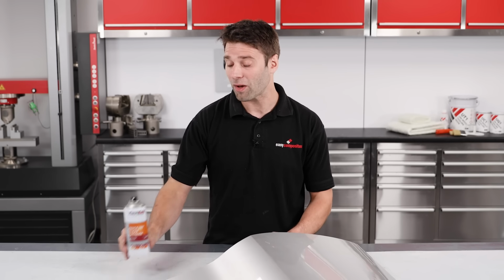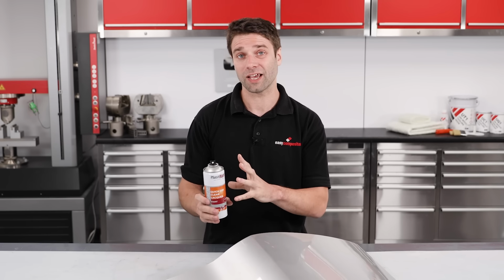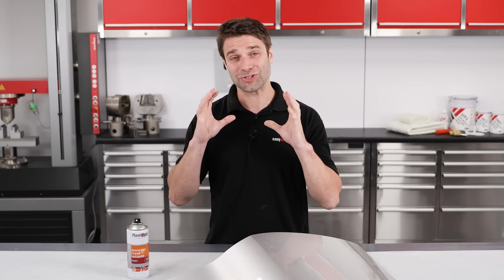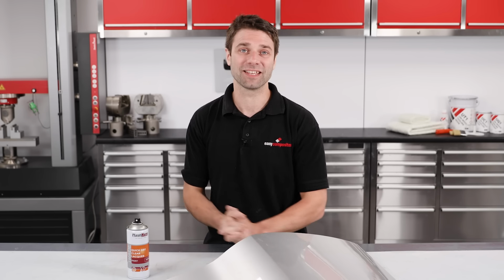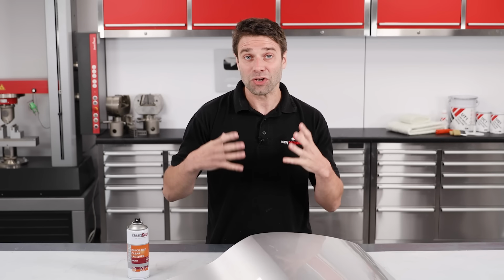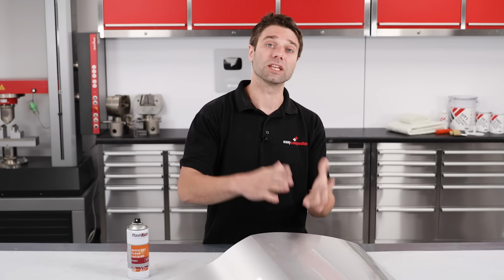Oven cured 2K paints do not generally react with the system. However, and probably the most common mistake that we find people will make is to paint a pattern with a 1-part gloss or clear coat. Now these will nearly always get attacked by the solvents found in vinylester and polyester gel coats, and so I would strongly advise never attempting this. Even when you're using good quality 2K paints, you can still have problems if it's not been fully cured. So generally you're going to need to oven cure the part before pulling your mould.